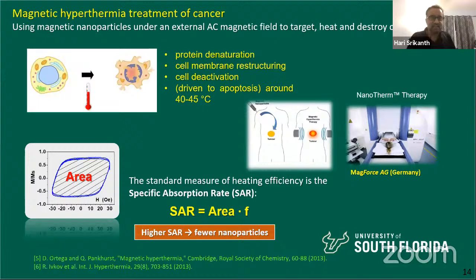This one looks like that, but it is not like any magnetization curve, right? This is strange. And the reason this is strange is because this is the AC hysteresis. This is the high frequency hysteresis loop. It is not the hysteresis or the magnetization that you measure in a magnetometer like a SQUID or a VSM, for example. That's the DC measurement, right? So this is high frequency hysteresis.